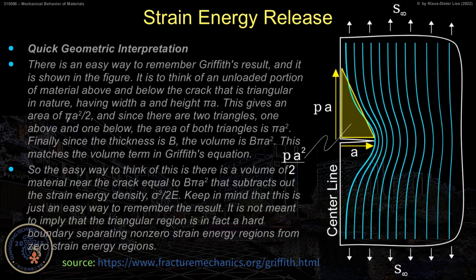This gives an area of pi A squared over two, for the triangle. And since there are two triangles, one on top and one on the bottom, not shown here, it becomes pi A squared. Finally, since the thickness is B in the third dimension, the volume is B pi A squared, and this matches the volume term in Griffiths' equation.